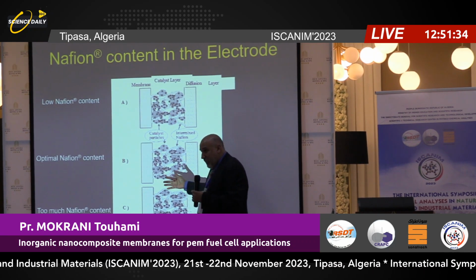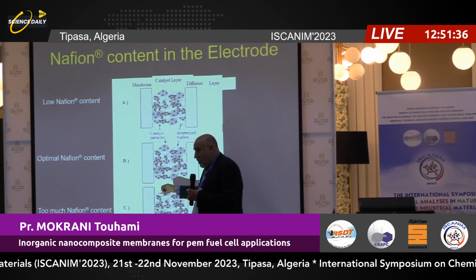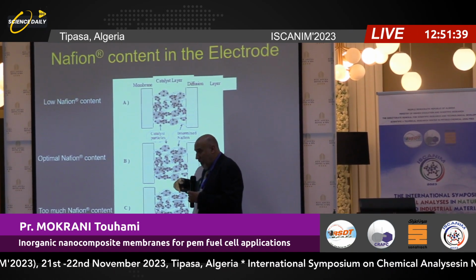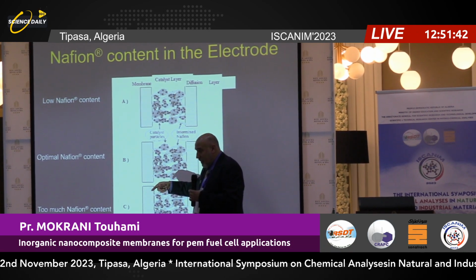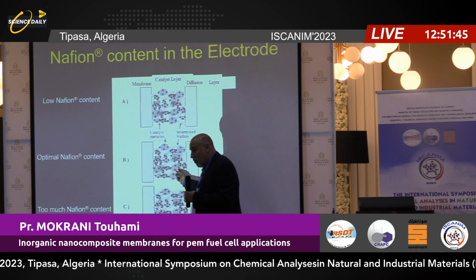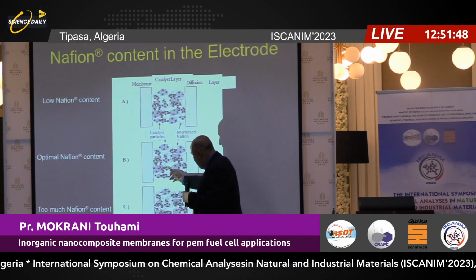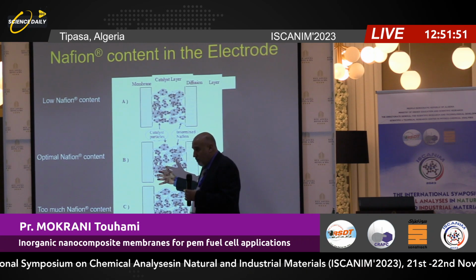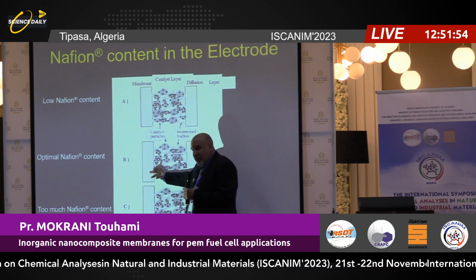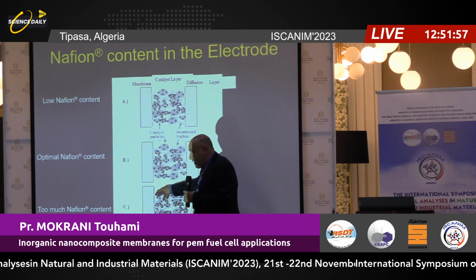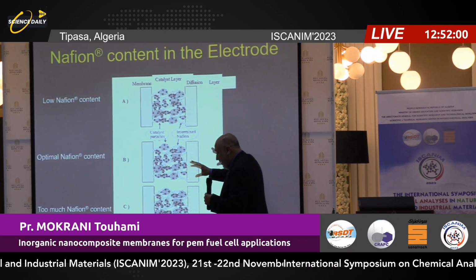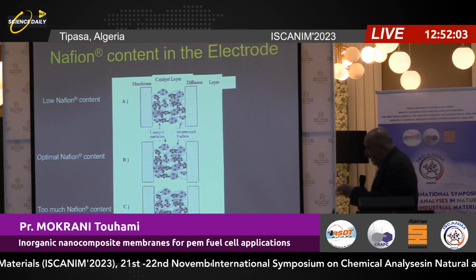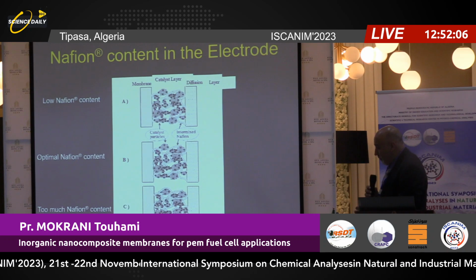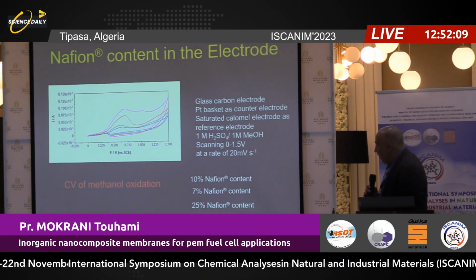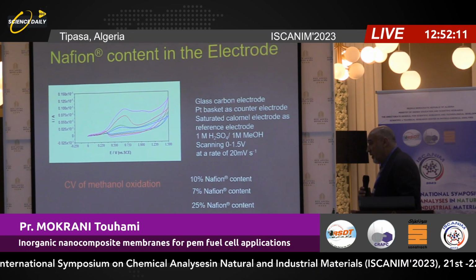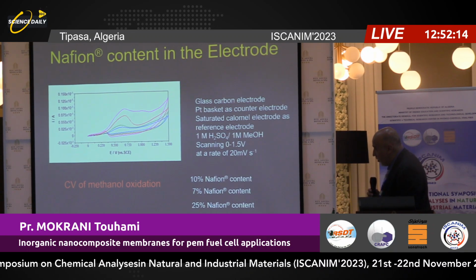At the beginning they struggled, then they decided to introduce something, because platinum is on carbon. So you have the electron path, but you don't have the proton conductive path. If this chain breaks, your protons will stop. So you need a carrier, and Nafion is one of them. So they mix Nafion solution in the electrode. It's not easy, but they developed it for Nafion. So any other material you will find is not performing as it's supposed to. You also need to develop or look for the electrode.